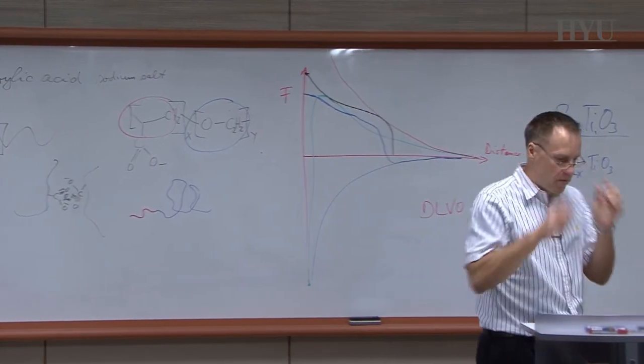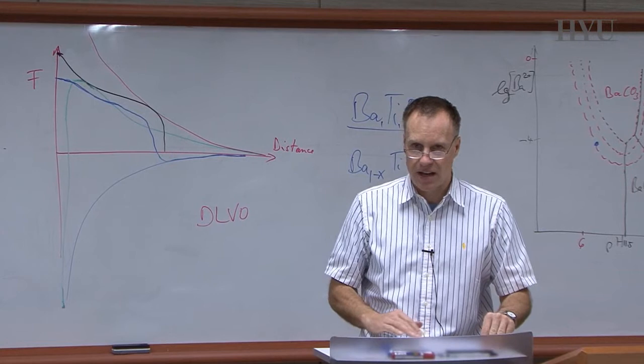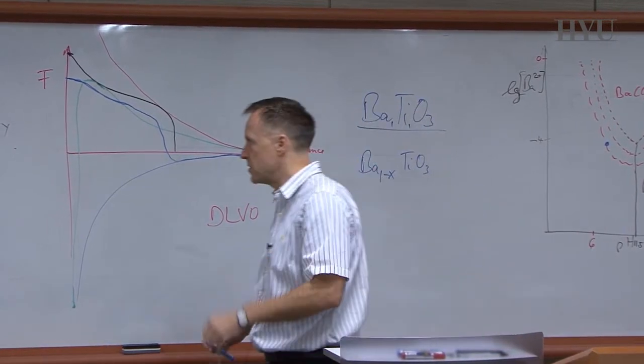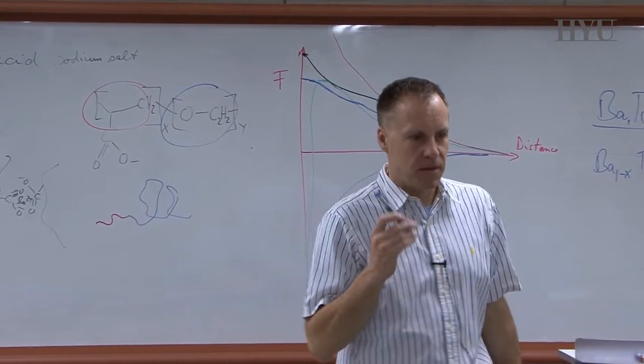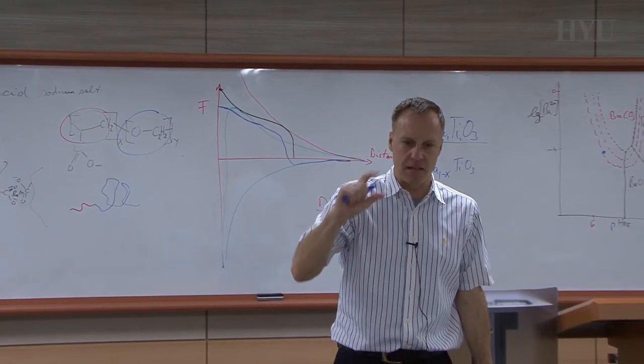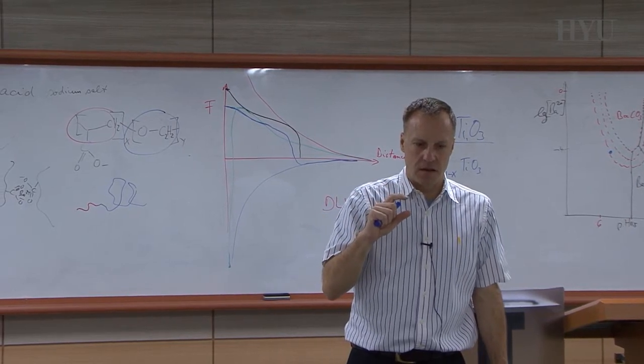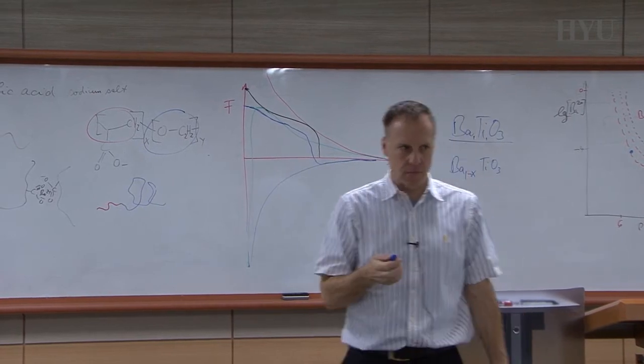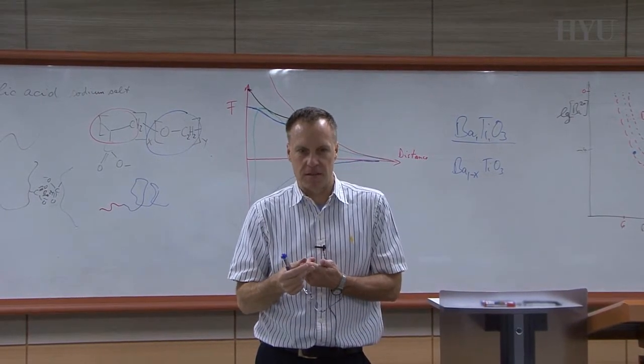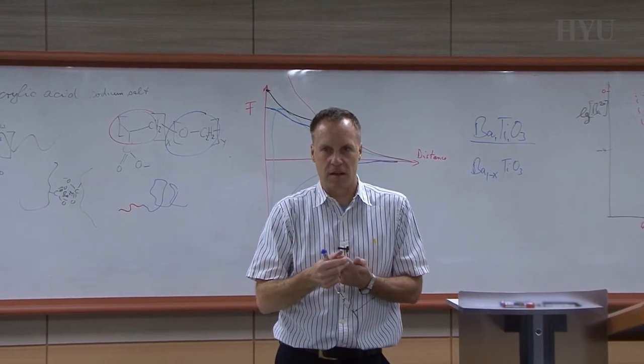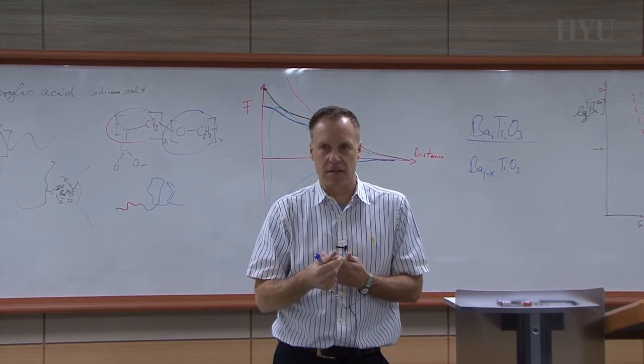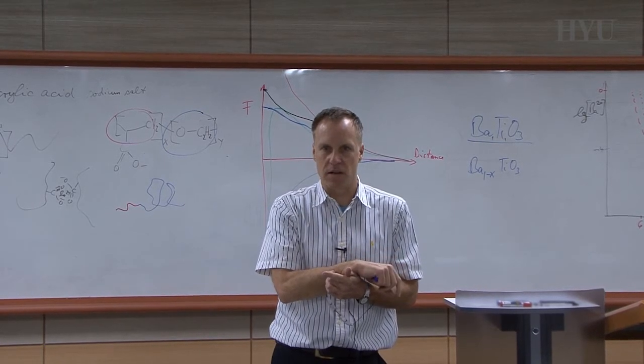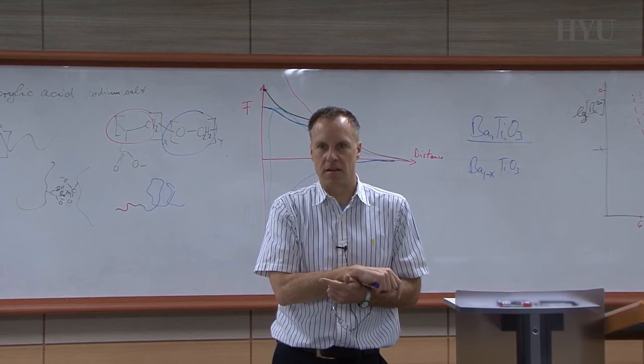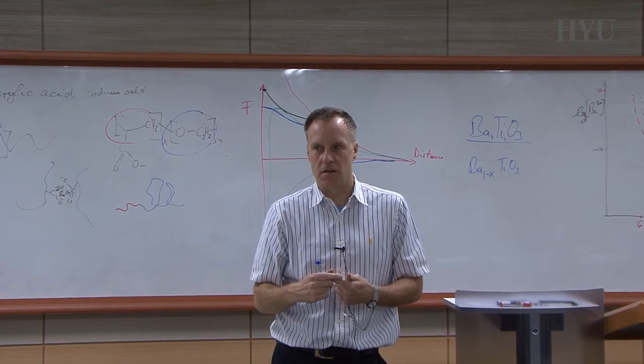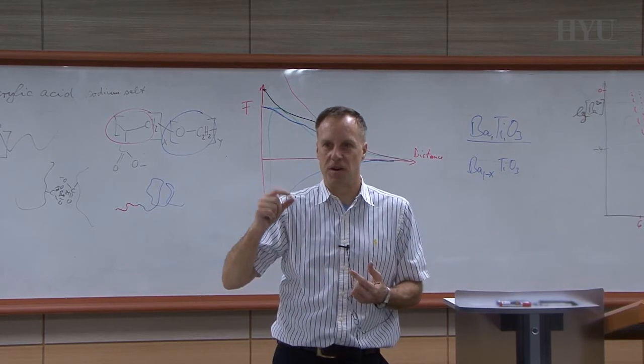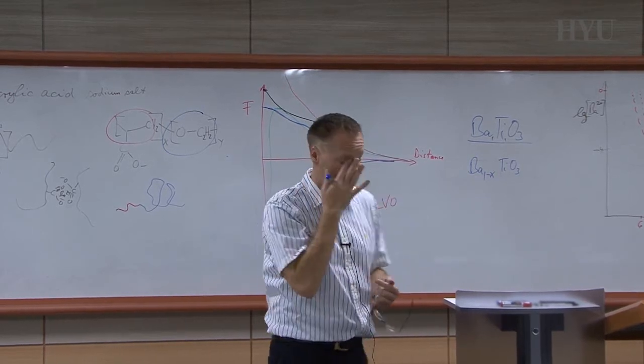And they really built already capacitors like this. They have in the order of like 100 nanometer, 200 nanometer layers of barium titanate or strontium titanate in there. But there are also enormous challenges there, because now you're in a size range where these materials change their properties. First of all, barium titanate, if the grains that you have in there are smaller than 30 nanometers, are no longer in the tetragonal state. They're actually changing phases and become cubic. And in that cubic state, there is no high dielectric constant. Yeah? So that is a disadvantage. So suddenly your capacitor, even though you use the same material, drops dramatically in performance.